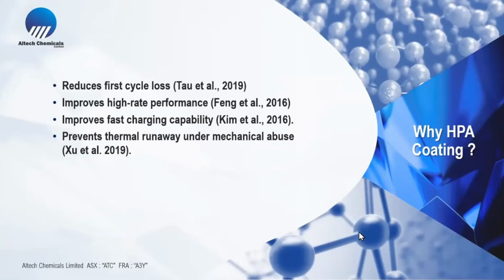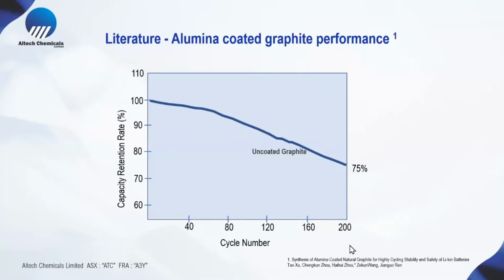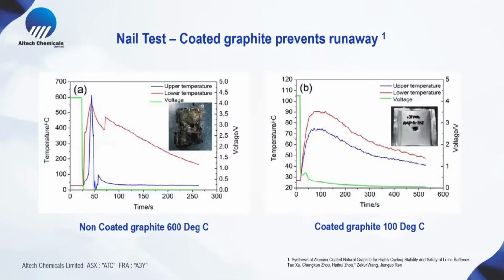Now, why is alumina being used on the graphite side? It's been proven by a lot of research around the world that it improves the first cycle loss, improves the high rate performance, improves the fast charging capability, and also improves the safety of the battery. So, for example, this is a typical piece of work where uncoated graphite versus coated graphite shows that the coated graphite battery has 10% more energy capacity after 200 cycles. So this is very important for the future.